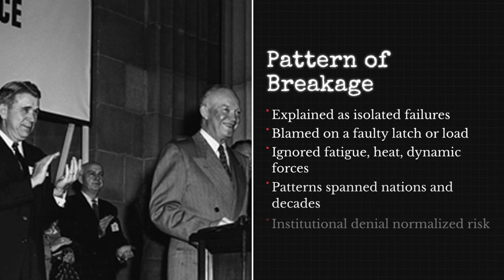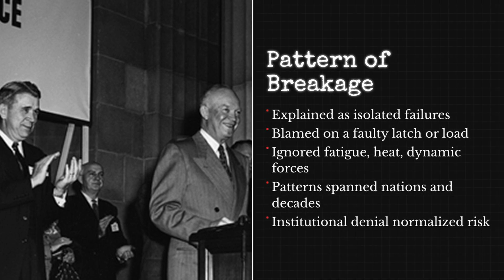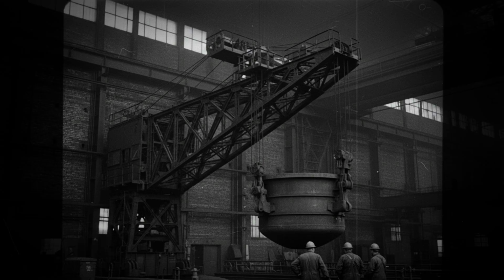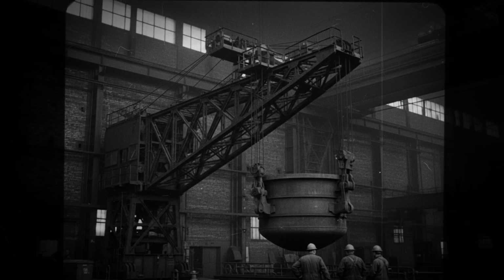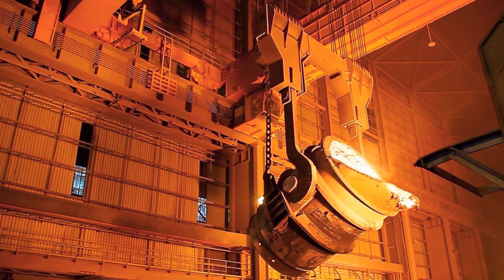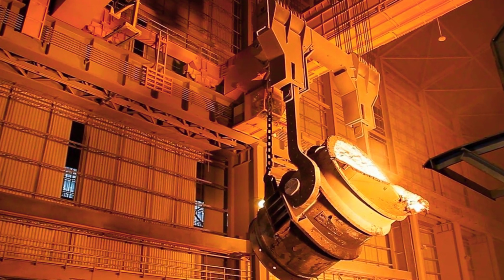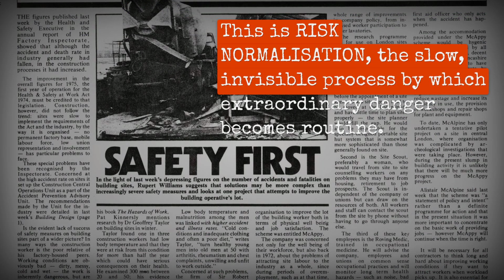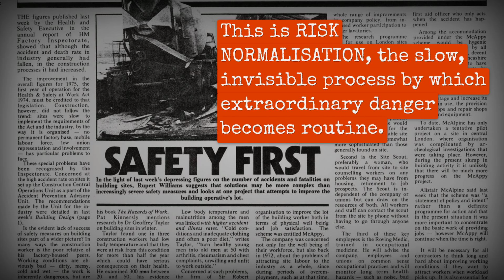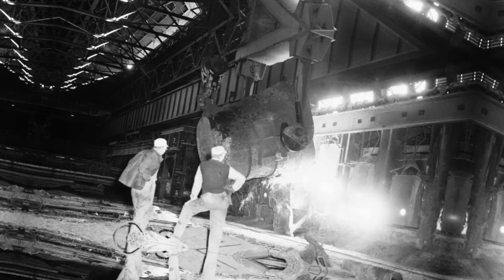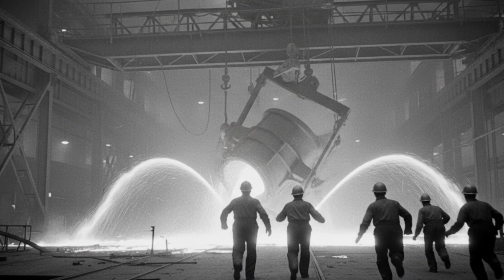Each investigation tried to explain the collapse as an isolated failure, a faulty latch, a misjudged load, a worn cable. But the records reveal something deeper, a mindset that treated each crane as a static structure, its limits defined by yesterday's calculations and the hope that nothing would go wrong today. This is risk normalization, the slow, invisible process by which extraordinary danger becomes routine. The Homestead rupture, the Sheffield collapse, the Gary disaster, each one different, yet all shaped by the same blind faith in numbers and habit. The Iron Beast didn't just fail once. It failed in the same way, again and again, because the system accepted risk as the price of progress.